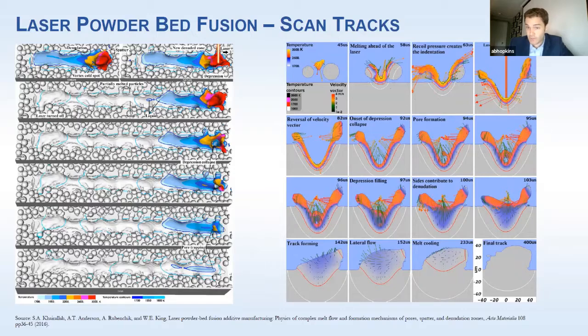The metal below the laser absorbs most of the laser energy. The powder absorbs a little bit of it. And then as you move, you create this melt pool. Particles are blasted. If you've seen a high-speed video of this, particles are blasted all over the build chamber. They fall in from the sides of the melt pool into the melt pool, and they fly out due to, basically, they're little rocket ships.